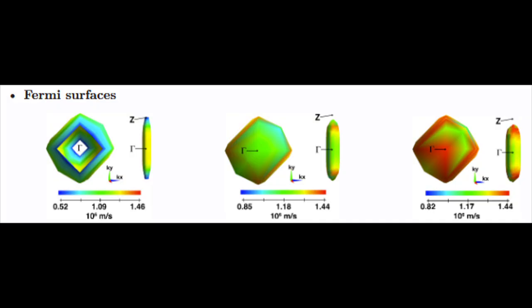Finally, the Fermi surfaces without the spin-orbit coupling effects are shown below with a color map indicating the Fermi velocities. An evolution of the surface as a function of the variable X is observed, where the quasi two-dimensional character of the iron selenium compound surface is lost with the addition of tellurium, tending towards a more spherical surface typical of 3D materials. The isotropy is broken in the k sub x, k sub y plane, and the Fermi velocity increases in proximity of the Z high symmetry point with respect to iron selenium.